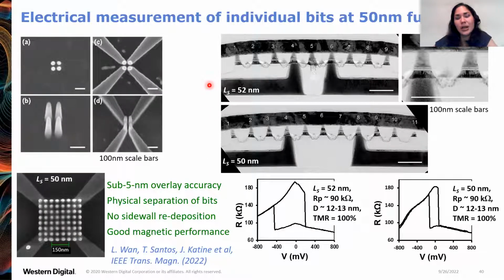At the top is a 52 nanometer full pitch array, and the lower one is a 50 nanometer full pitch array. And with these images, you can see very good alignment of these multiple E-beam lithography steps to get the contact pillars and the arms and the bits all lined up. We confirm physical separation of the bits. We see that we have removed the redeposition of the sidewalls because we can perform the electrical test and confirm good magnetics by seeing a TMR value of 100%.